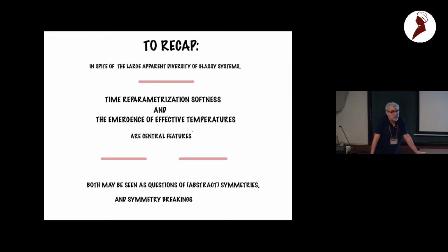Because we know that the shape is the same, but the amplitude is different, so it's not only the time in the fluctuations. But it's not inconsistent. It's not only a time reparametrization, but you're looking at a fluctuation. The fluctuations grow with the softness, and that is not the quantity that is reparametrized, that is the amplitude of the fluctuation, which is consistently becoming higher. But it's roundabout, and it's not in contradiction.